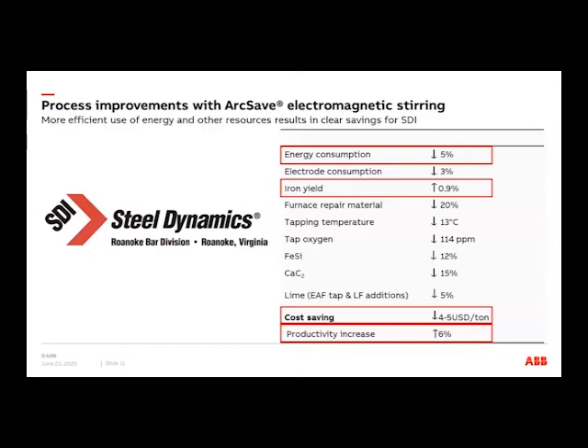Other benefits which we saw from SDI Roanoke was smoother tapping conditions. We had a free EBT opening from around 70% up to 96% when we were using the stirring during the tapping. We also had less carryover slag to the ladle because we could kill the vortex which forms during tapping of an EBT furnace at a later stage.